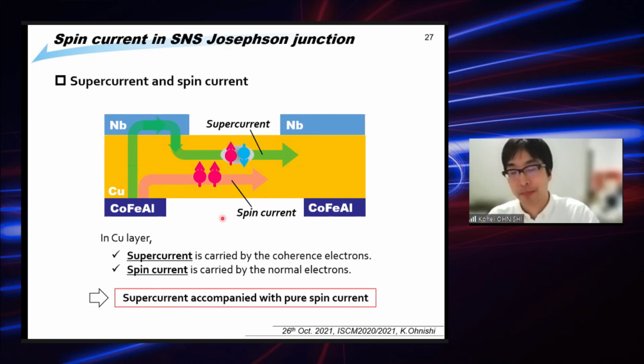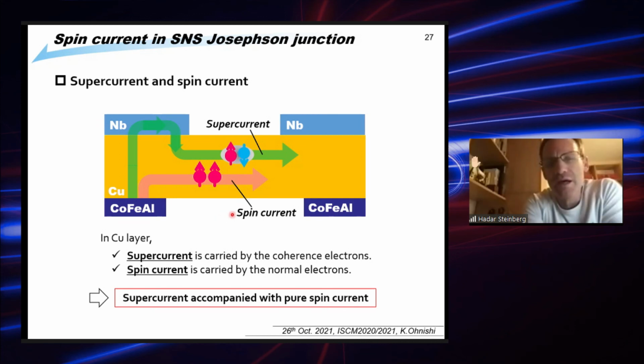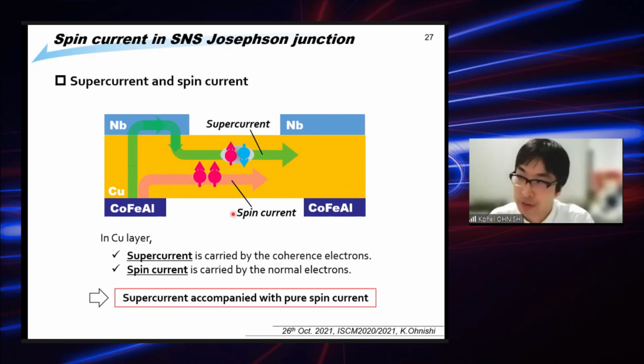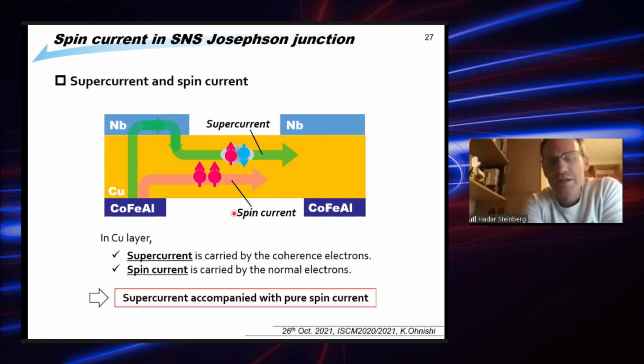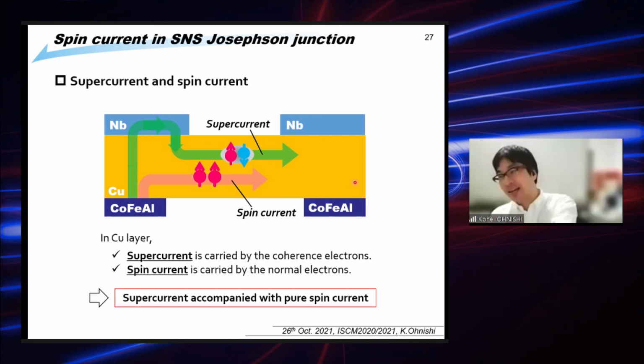I'm saying if you look, for example, at the papers by the Delft group on graphene, Tombros et al., the 2007 papers on graphene spintronics, the spintronics community uses a certain language, and this language has to do with the spatial dependence of mu up and mu down along the channel. That's a certain formalism that's used, and generally you can argue that the further away you move from the injection point, the spin-up potential and spin-down potential gradually grow together. Now, here you're doing something very interesting. You add a third population, which is the Cooper population. I wonder if you have in any way considered this formalism, and the fact that your system can simply be out of equilibrium.